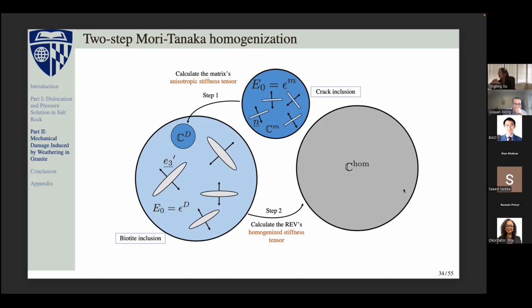So in order to avoid any mistakes in the stiffness tensor, we have this two-step homogenization scheme. The first step is that we calculate the crack inside this undamaged matrix, and we calculate the anisotropic stiffness tensor for this damaged matrix. And the second step is that we calculate the biotites that are embedded in this damaged matrix. We get the finalized homogenized stiffness tensor, which is the C homogenized here. And that is also the value that enters into the free energy of the REV that I just mentioned.